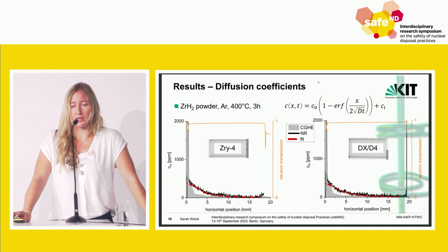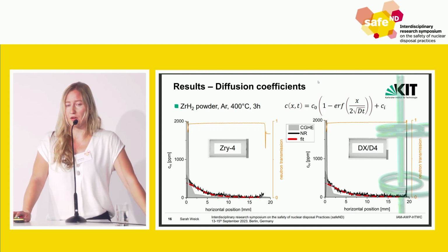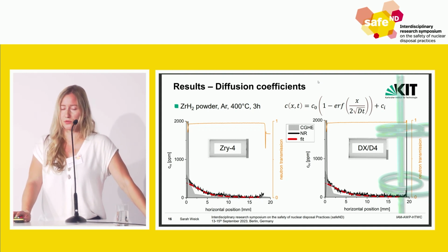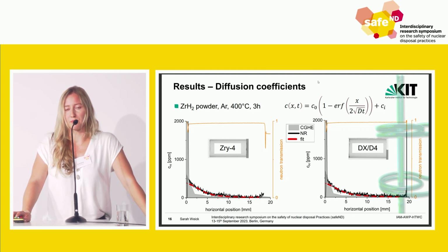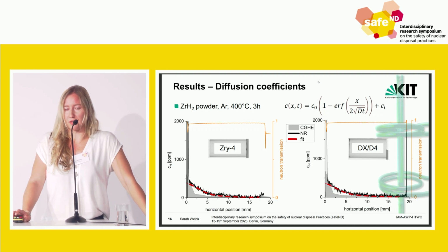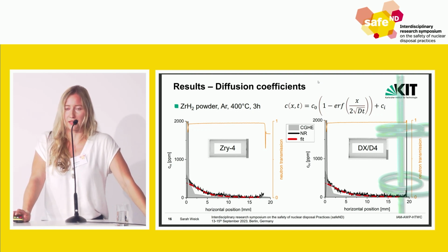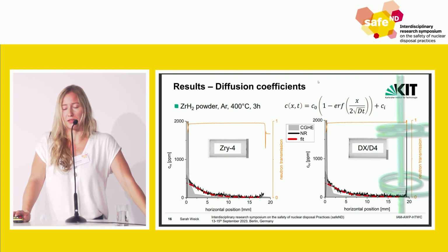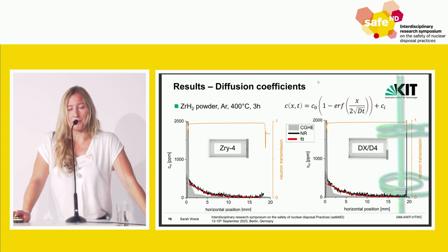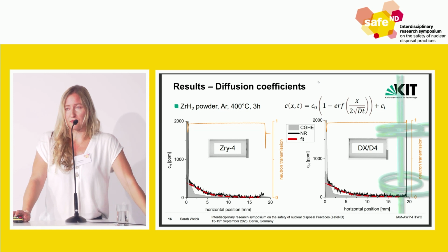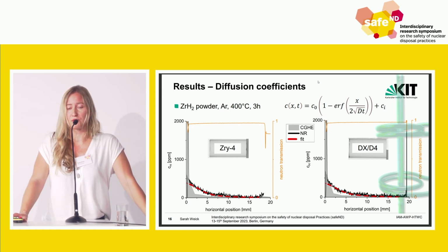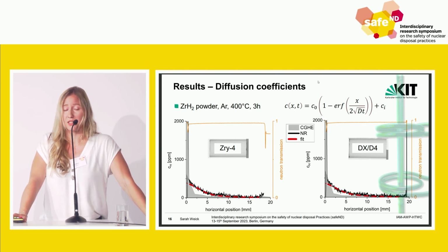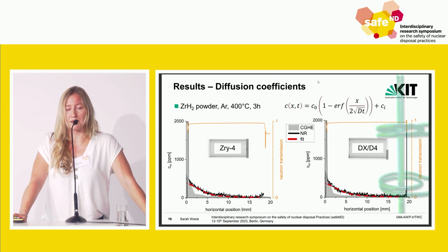Then you would be able to calculate some diffusion coefficient, so how fast is the diffusion in those cladding tubes, also in relation to the diffusion direction or the actual orientation of those cladding tubes. You also need a time-dependent factor, because the zirconium oxide forms directly in contact with air, which means before the hydrogen diffusion can start, we need to dissolve this zirconium oxide again, and then the hydrogen diffusion would start.